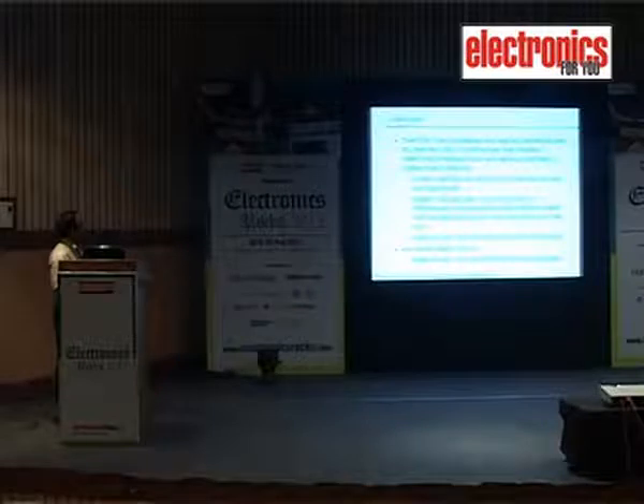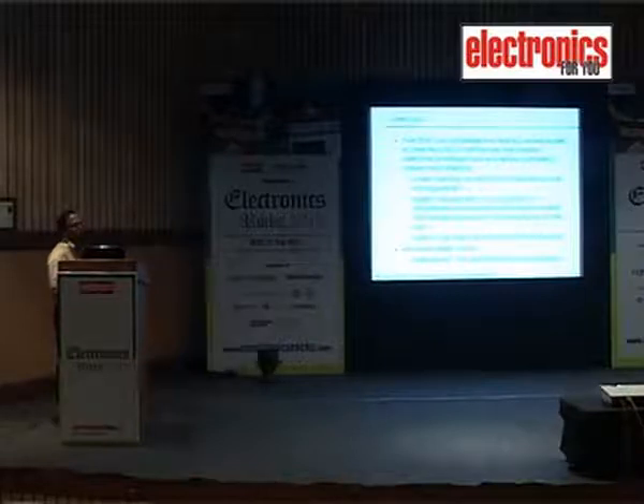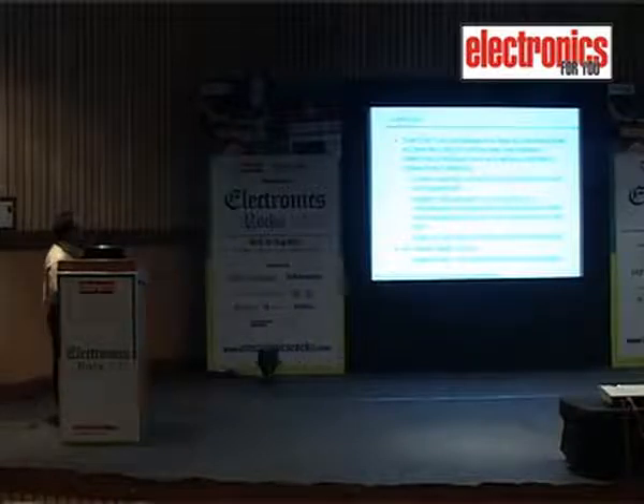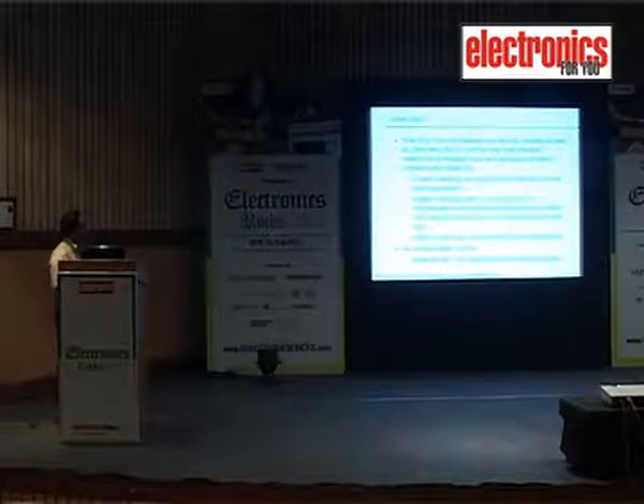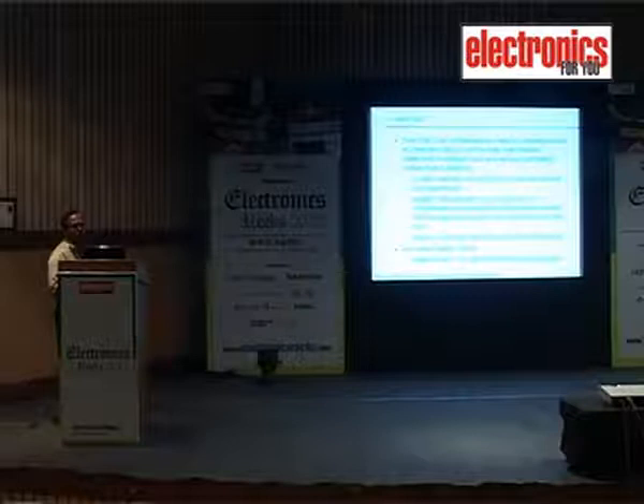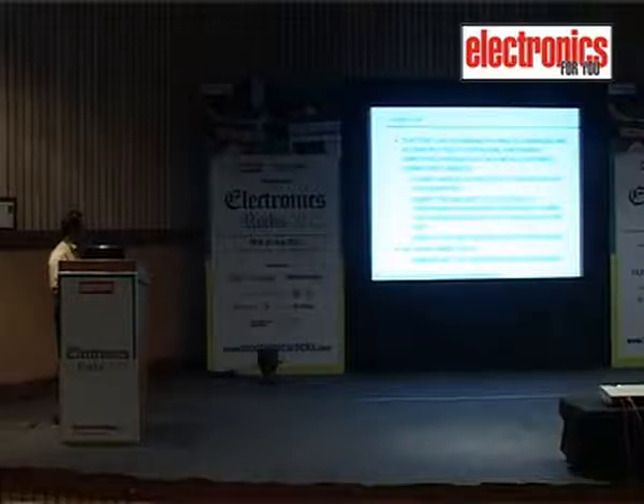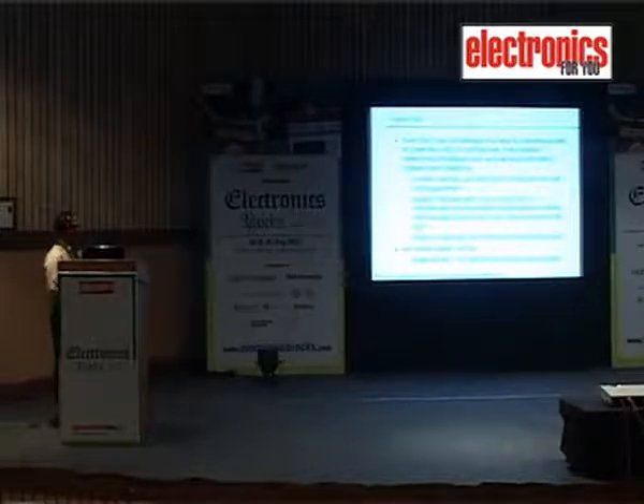For these vibration checks, we have a vibration table where we mount the PCB, clamped at 4 places and supported with 4 studs, and then we sweep the sine input, a vibration input, from 1 Hertz to 2000 Hertz, and we determine the resonance frequency by mounting the transducer at the middle of the PCB. Then at that resonance frequency, we continuously vibrate the PCB for 30 minutes. After vibrating for 30 minutes, we do the bareboard test and we do microsection to observe any deformation in the barrels, which are very critical.